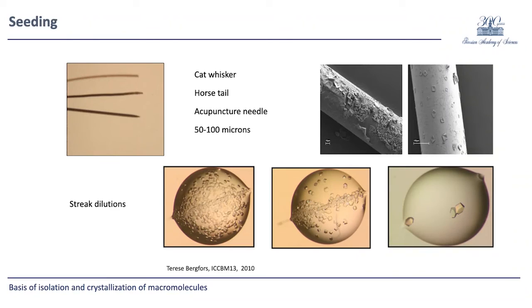If we recall the crystallization diagram, there is a metastable zone where crystals do not nucleate, but can grow. Therefore, if you add crystals from another drop to a drop that is in a metastable state and unable to reach the state of crystal nucleation, then they appear in conditions favorable for growth. It will begin to grow actively. In this way, we will be able to obtain individual large crystals. The number of transferred crystals and their size are selected experimentally.